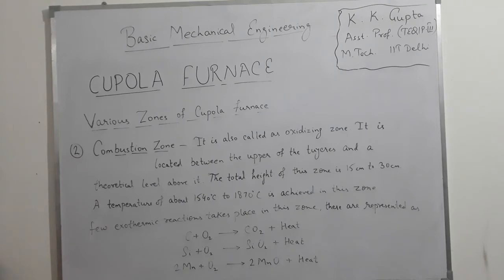Second zone is combustion zone. It is also called as oxidizing zone and it is also called as superheating zone. It is located between the upper of the tuyeres and a theoretical level above it. The total height of this zone is 15 cm to 30 cm. A temperature of about 1540 degrees Celsius to 1870 degrees Celsius is achieved in this zone. Few exothermic reactions take place in this zone. These are represented as carbon plus oxygen gives carbon dioxide plus heat, silicon plus oxygen gives silicon dioxide plus heat, manganese plus oxygen gives manganese oxide plus heat. The combustion actually takes place in this zone by consuming the free oxygen completely from the air blast and generating tremendous heat.